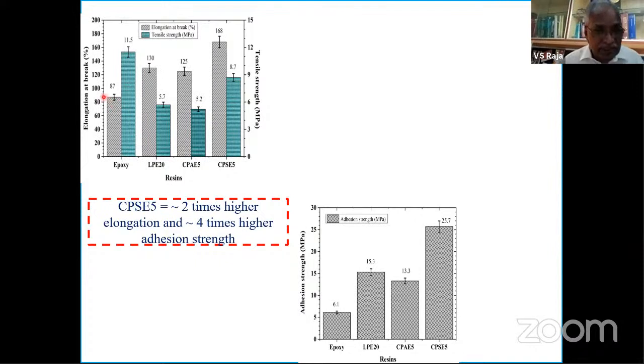Now, these are the data with respect to the elongation. Please see here, the elongation of these particular polymers. These are all freestanding epoxy films. Look at this now. This is the elongation to break, tensile strength. Now you see this elongation to break. This is your modified polymers. So look at this here. Now the elongation has increased from 87% to 168%. That means it has really good toughness as compared to neat epoxies. Of course, when I increase the elongation, you're going to lose on strength. But in this case, you can see here, the strength is still better as compared to the other two modifications.